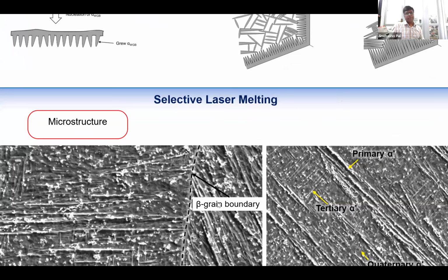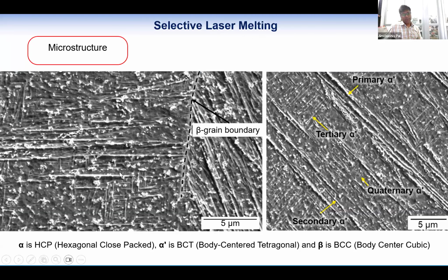And in selective laser melting, there is a very fast cooling rate, and also the layer-by-layer heat cycle effect. That's why there is formation of a hierarchy of martensitic structure, like alpha prime martensitic needles. There is the primary, the bigger one; the secondary is quite a bit smaller; and the tertiary and quaternary are much smaller. Such a hierarchy is formed so that when a crack starts, it gives more strength and protects against crack growth.